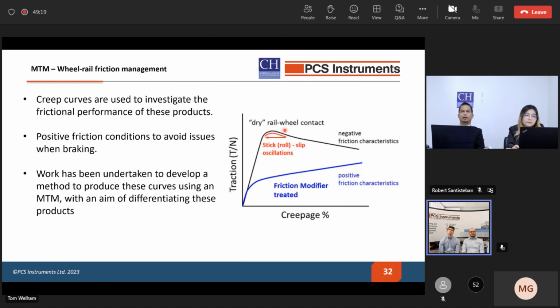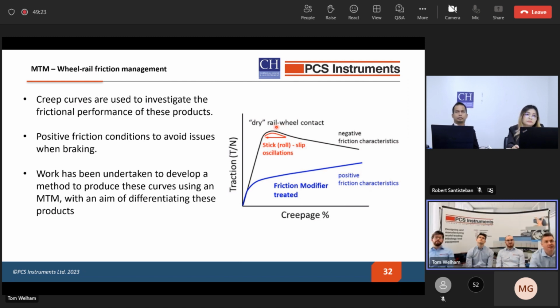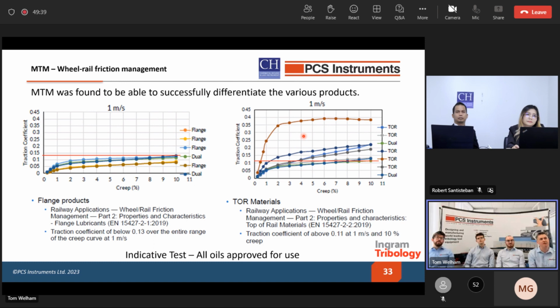So the use of friction modifiers in these top of rail products allows us to have what we call positive friction characteristics. So as sliding increases, the traction coefficient increases. So we have this sort of behaviour, which means we never get into this unstable oscillation. So there was a study into this using the MTM, and it was found to be very well able to differentiate between these different top-of-rail products.